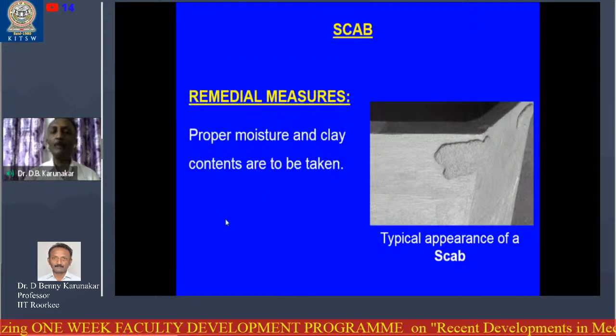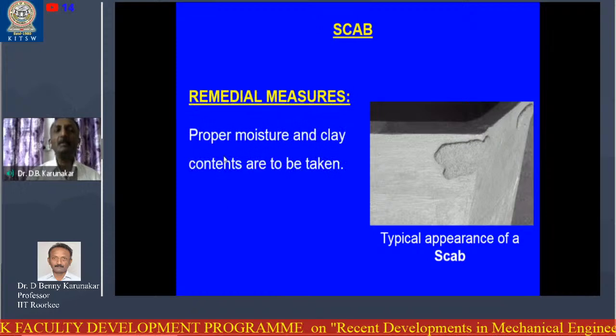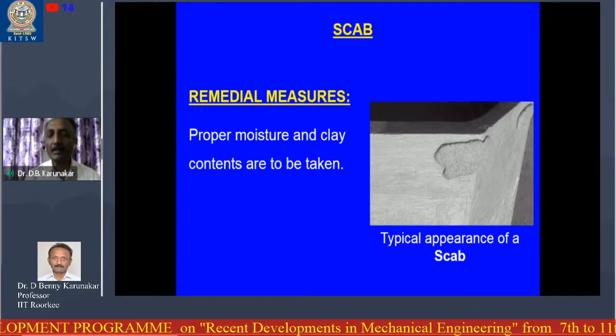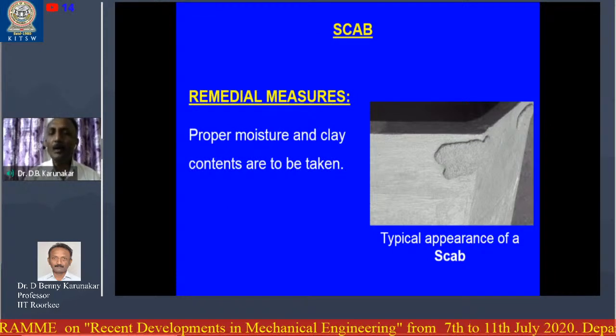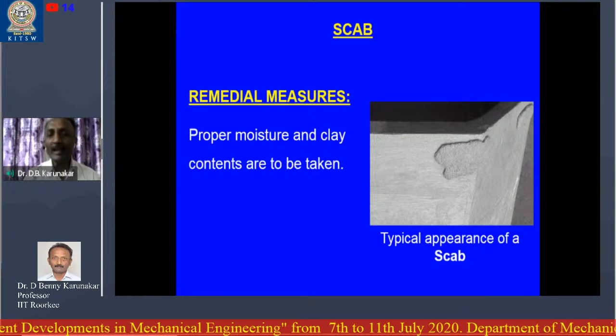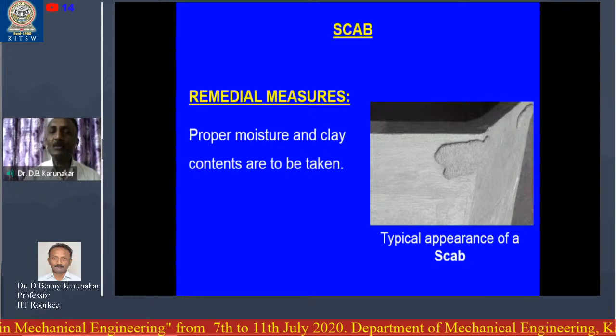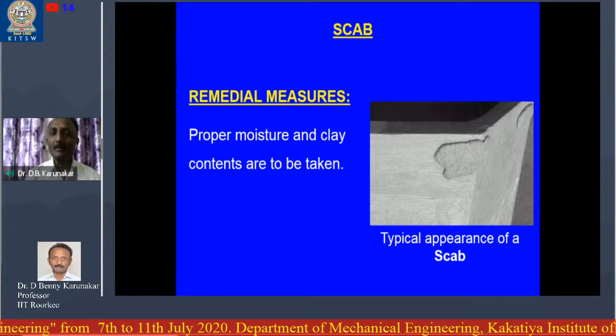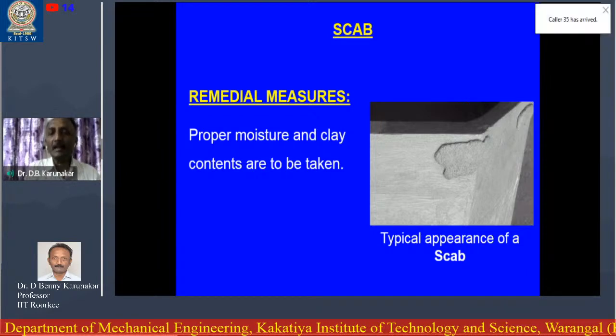How to prevent this? Regulate the moisture and clay content. Don't use too much moisture content, but it doesn't mean you should use too little either. The moisture content should be sufficient. Also, the clay content should not be too much. If the clay content is too much, the mold becomes very hard and strong, and it becomes very difficult to break after solidification, and permeability becomes very poor.